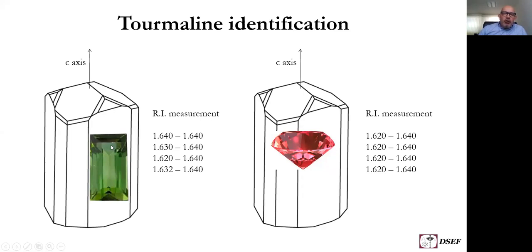Now, in green tourmalines the pleochroism is very extreme, so that if you look in the direction of the optic axis, the stone is almost black. So green tourmalines are commonly cut so that the table is parallel to the optic axis, and so you commonly have elongated shapes in green tourmalines. Whereas in red tourmalines, the color that you see perpendicular to the optic axis is too light. So the most attractive color is the color that you see when you look into the optic axis, and for this reason, pink to red tourmalines are commonly cut in more rounded shapes.